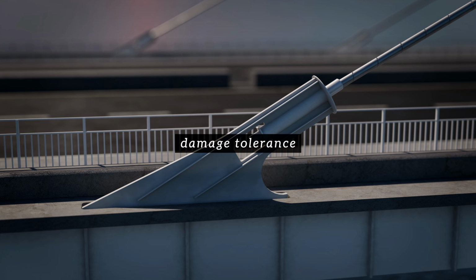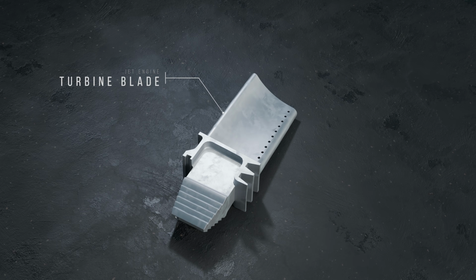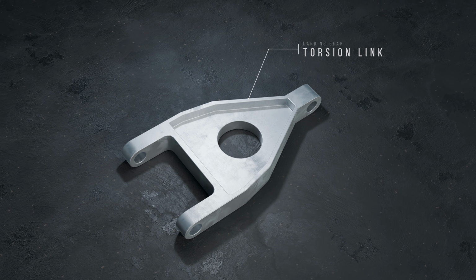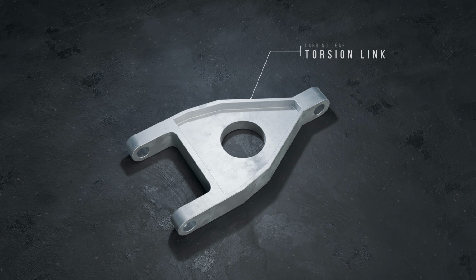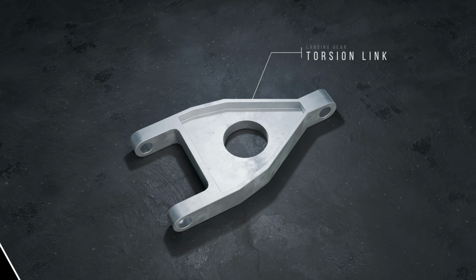Instead of assuming a perfect, defect-free structure, the damage tolerance approach accepts that cracks will exist and focuses on making sure they can be detected, monitored, and if necessary, repaired before they reach a critical size. This approach is widely used in aerospace, where it emerged in the 1970s. Aircraft components like jet engine turbine blades or landing gear parts are inspected at regular intervals to identify and size cracks. This is done using non-destructive testing techniques like visual inspection,